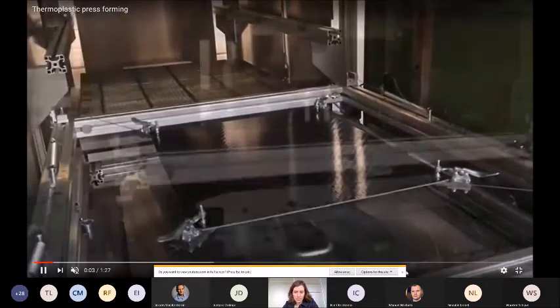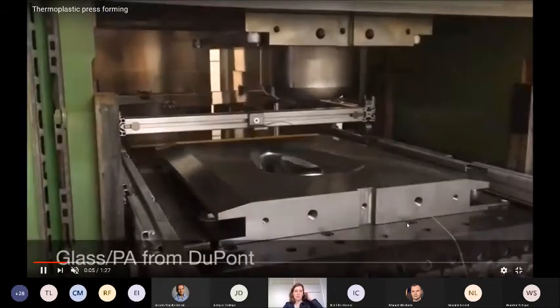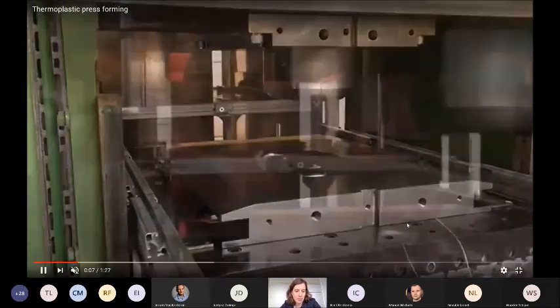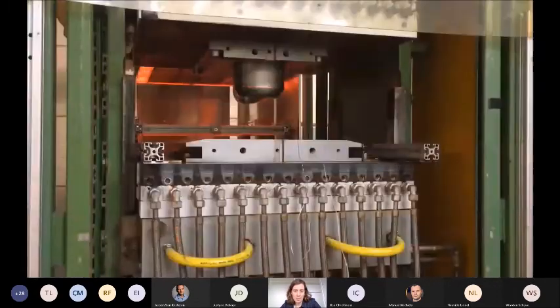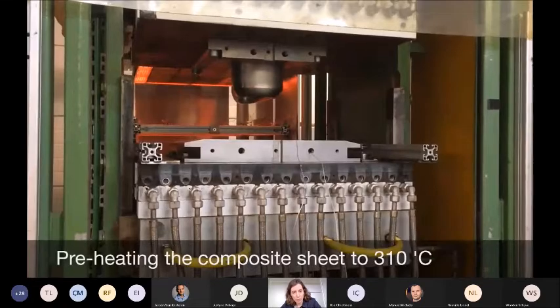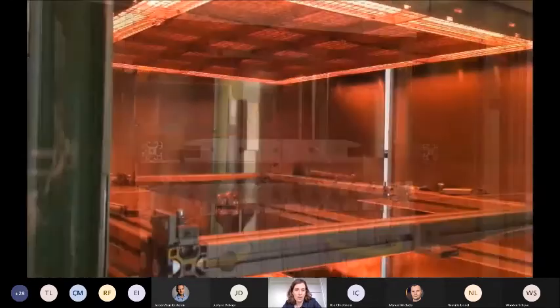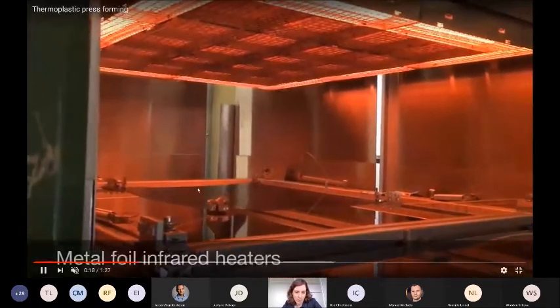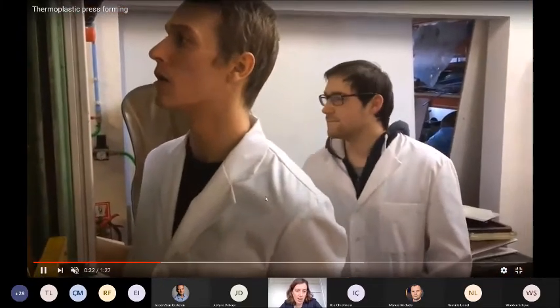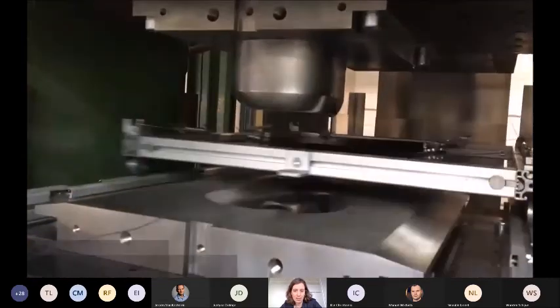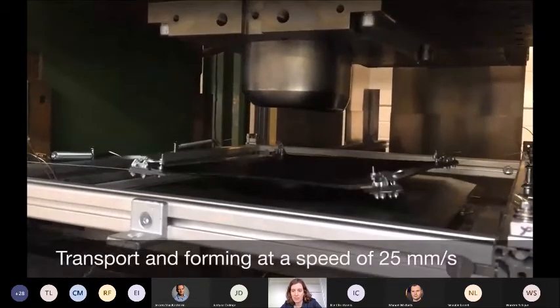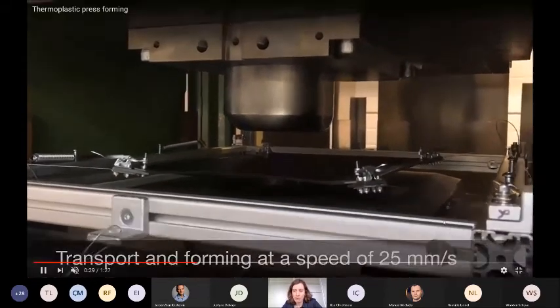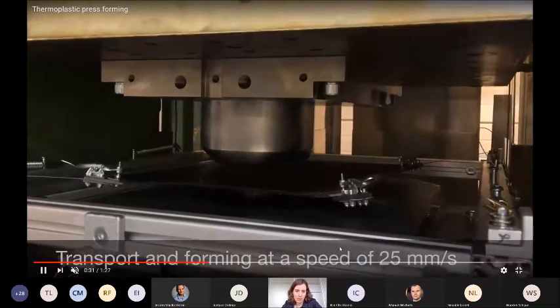Voila. Okay, so this process describes the press forming of thermoplastic composites. It's a two-step process. So first you do a preheating under infrared heating. Here you see the thermoplastic sheet, which is clamped. This is also a lab scale test, by the way. So this is with a very versatile clamping unit.